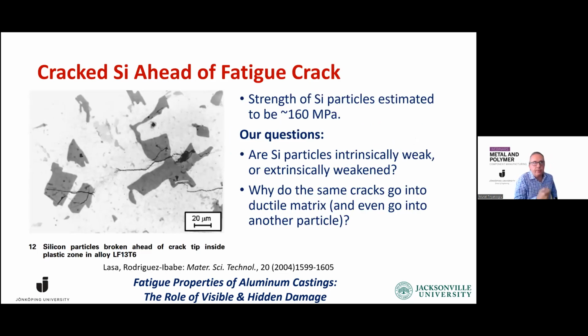Another example, I've already shown you the silicon particles broken. Here's another example. This comes from a fatigue paper. The silicon particles broken ahead of the crack tip inside the plastic zone, reads the figure caption. And the authors estimated the silicon particle strength to be about 160 megapascal based on fracture mechanics. Okay, sound calculations. But our question is, are they intrinsically weak or extrinsically weakened? And again, why do the same cracks go into the ductile matrix? If these are weak and brittle, why is the ductile matrix not able to absorb that kind of strain?